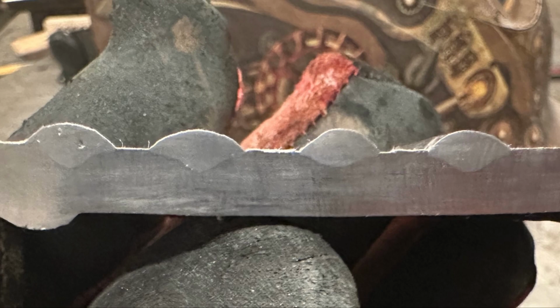But my thoughts are, if you look near the toe of the weld for the gas shielded, it seems to have a rounder profile, almost like the penetration near the toes is better. So it's like the overall average penetration is more consistent, but the actual depth is less. So kind of interesting. Let's look at the other side of the plate now.